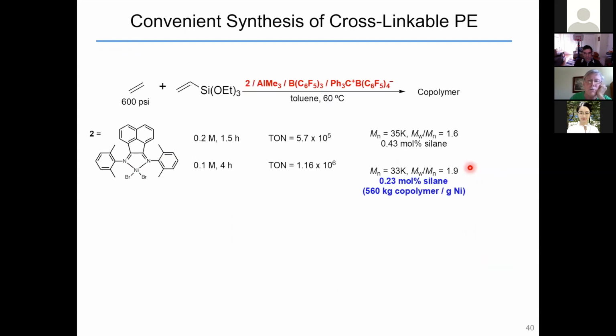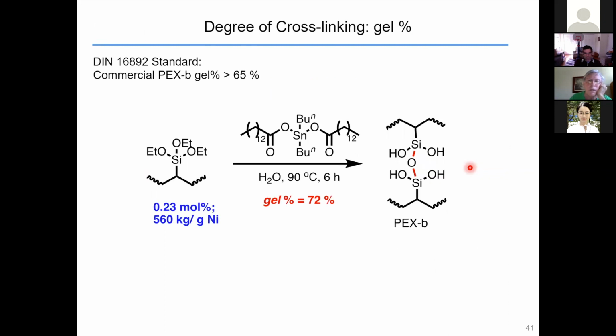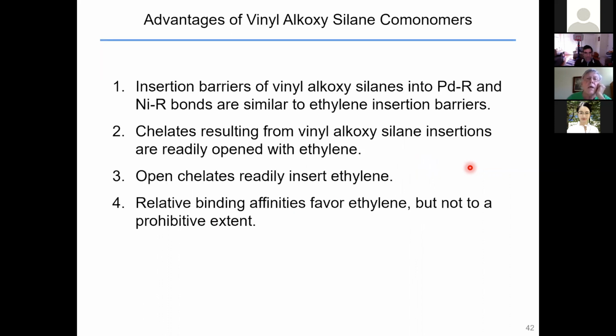So I'll go on to the conclusions here, since I think I was supposed to speak for 40 minutes and we're at 45. So here are the advantages of the vinyl alkoxysilane comonomers in these late metal polymerizations. The insertion barriers of the vinyl alkoxysilanes into the palladium alkyl bonds and nickel alkyl bonds are similar to the ethylene insertion barriers. The chelates that result are readily opened with ethylene, unlike the ester case.